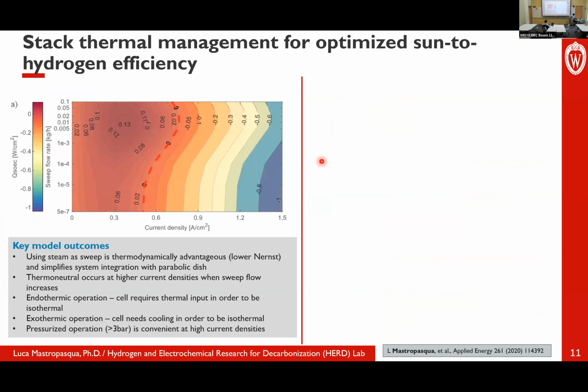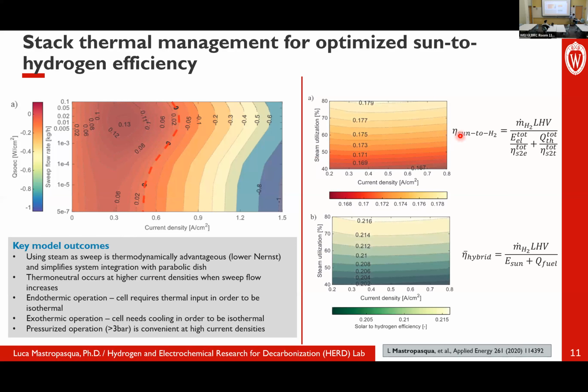The efficiency of the process is a function of the operating condition of the SOEC. This figure is a bit complicated, but it basically shows that at different current densities, there is a different thermal balance of the SOEC, because of what I explained earlier. Some conditions will be in endothermic mode, some in exothermic mode. In terms of efficiency, this is sun to hydrogen efficiency. Depending again on the operating condition, we can achieve 16 to 18% efficiency. So approximately 17% of the energy of the sun will be converted into the final hydrogen product.